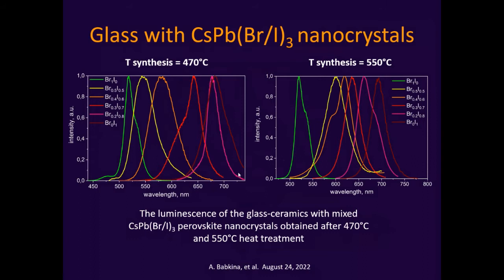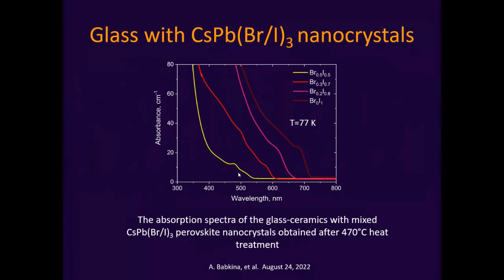The problem with this luminescent spectrum is that we have not got very selective excitation. Our excitation is really very wide, and maybe that is our problem, that because of it, we don't see 2 bands of luminescence. What about the absorption spectrum? Looking at the absorption spectra, we do have several bands. The first band in the long wavelength region, of course, corresponds to the iodide perovskite nanocrystals. The absorption band situated in the short wavelength region, about 500 nanometers, corresponds to the bromide crystals, and we see it separately. So we try to tune the excitation wavelength to excite our luminescence, but we still have one very wide luminescence band.